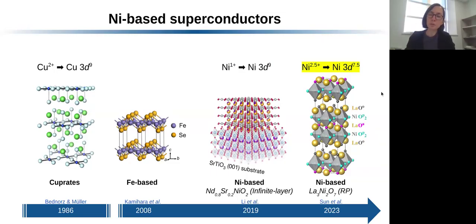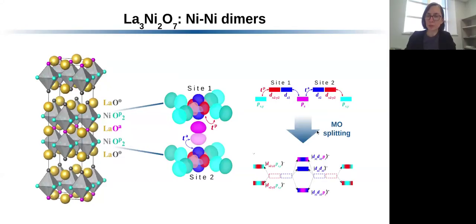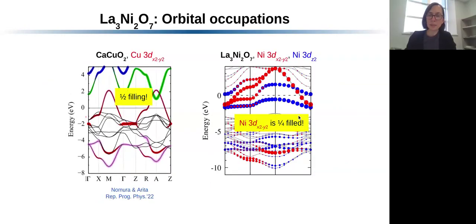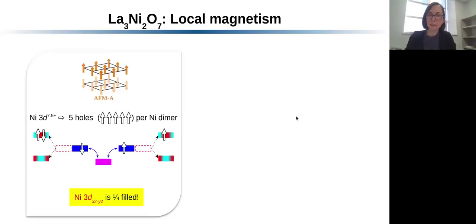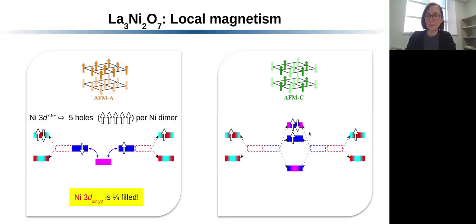What I was hoping to show you, but it looks like I don't really have time, is that despite these differences in the structure and also in the electron filling, because of the molecular orbitals, which I show in this slide, because of the molecular orbital splittings of the same kind I had in the hydrogen molecule system, I can have a situation, so let me go straight to that here, where I have molecular orbitals in the electronic structure, and that changes the occupation of the most important orbital for the superconductivity in both the cuprates and the nickelates, the x squared minus y squared orbital, which in the cuprates is half filled, and in this system is quarter filled if you don't do the molecular orbitals properly.